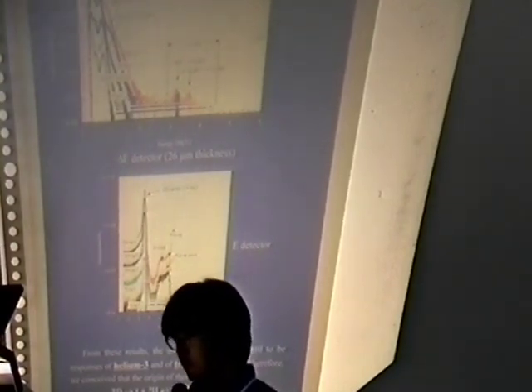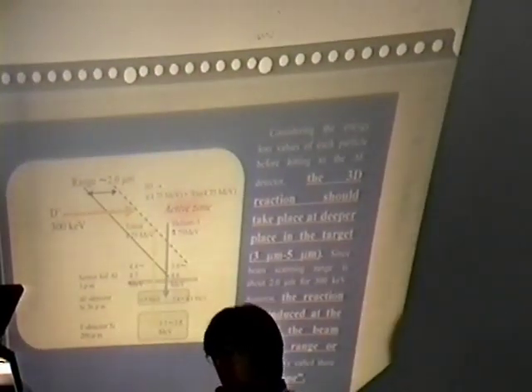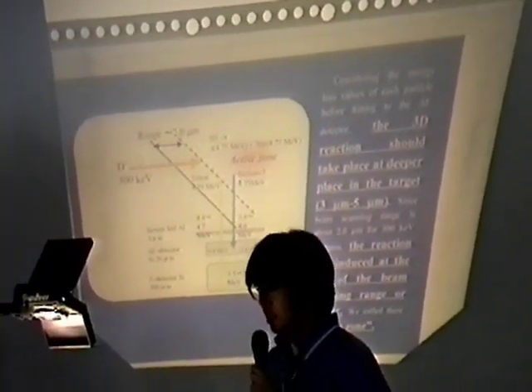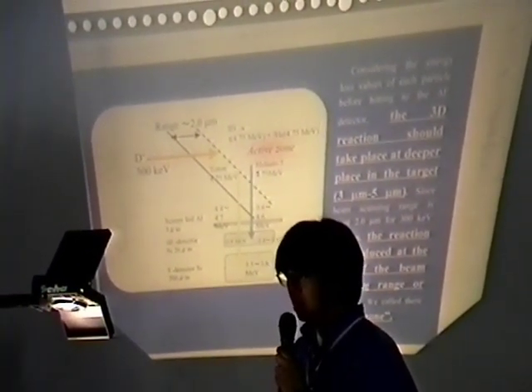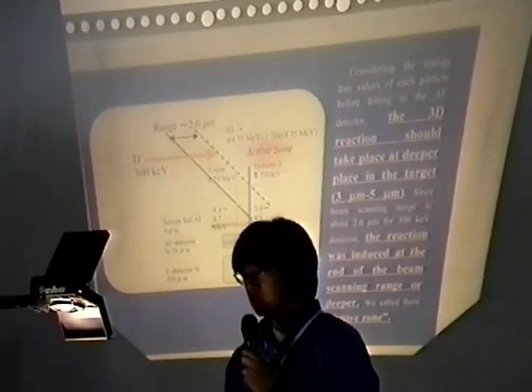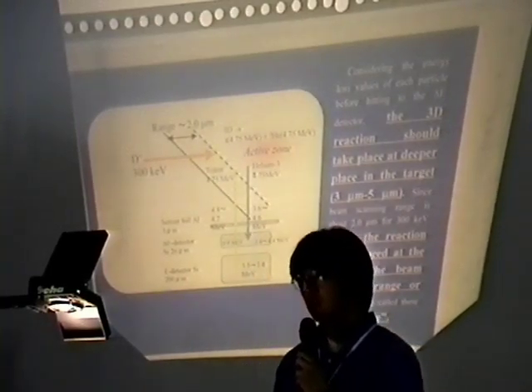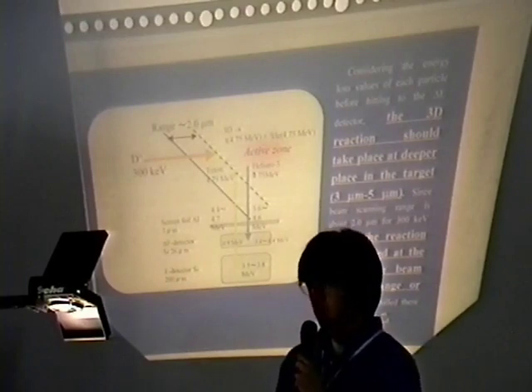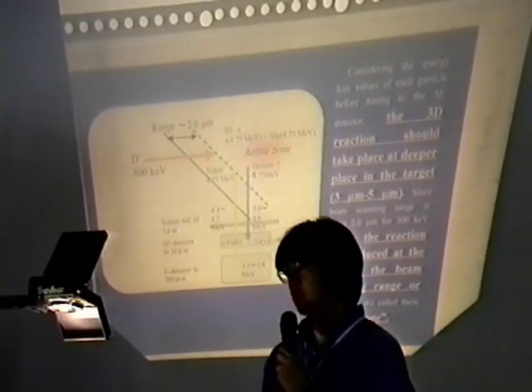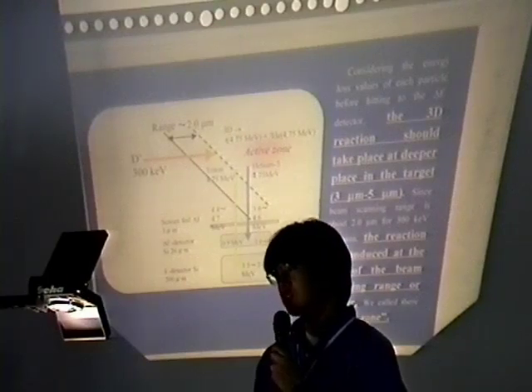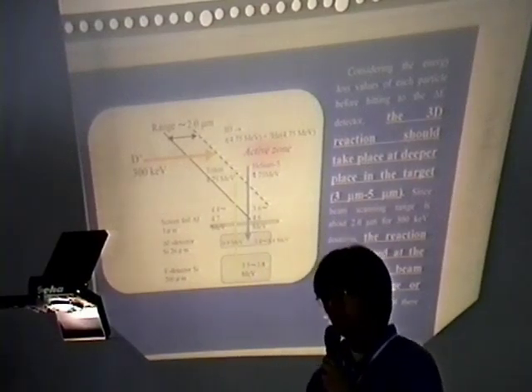Therefore, we conceive that the origin of this shoulder is this 3D reactions. But considering the energy loss values of each particle before hitting the detector, the 3D reaction should take place at deeper place in target, about 3 micron to 5 micron depth. Since beam scanning range is about 2 micron for 300 keV deuteron, the reaction was induced at the end of the beam scanning range or more deeper place.